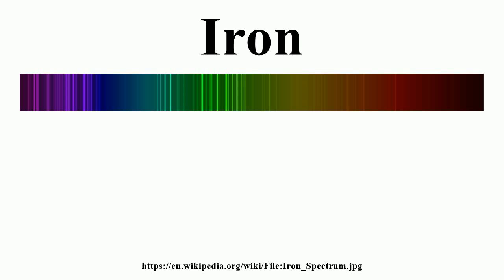This nickel-56, which has a half-life of about 6 days, is therefore made in quantity in these stars, but soon decays by 2 successive positron emissions within supernova decay products in the supernova remnant gas cloud, first to radioactive cobalt-56, and then stable iron-56. This last nuclide is therefore common in the universe, relative to other stable metals of approximately the same atomic weight. In phases of the meteorites Semarkona and Chervony Kut, a correlation between the concentration of 60Ni, the daughter product of 60Fe, and the abundance of the stable iron isotopes could be found, which is evidence for the existence of 60Fe at the time of formation of the solar system.